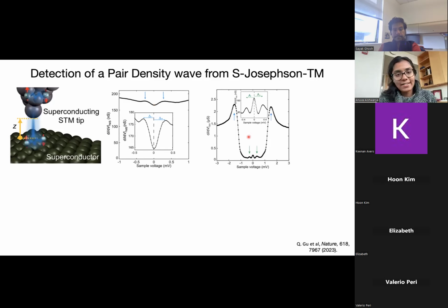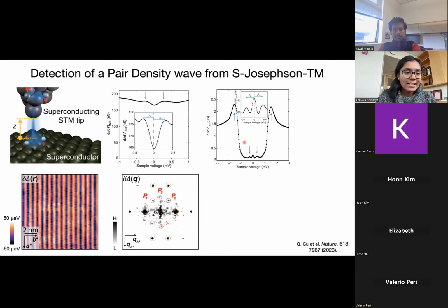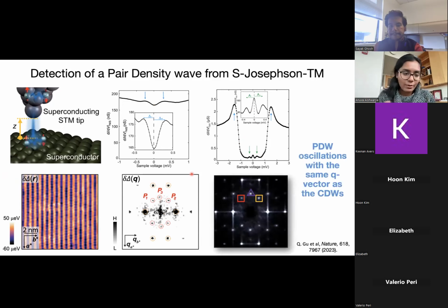What they see is that in density of states maps, they can see this delta delta is basically the oscillation of the gap size in real space. And if you take a Fourier transform of the oscillation of the gap size, you can see that it oscillates at the same Qs as what we see in our measurement. So this is actually direct evidence of the existence of a pair density wave in UTe2 with the same Q vectors as the CDW. So one question we can ask at this point is, based on our model, what do